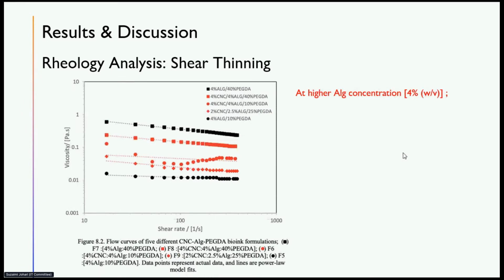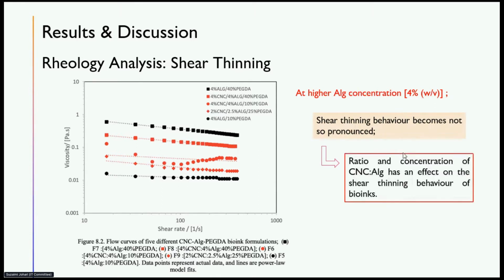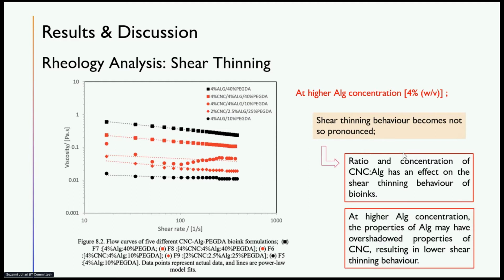Next slide. In figure 2, the flow curves show the other 5 formulations at higher alginate concentrations. At higher alginate concentrations, there is still shear thinning property, but it is not as pronounced as the shear thinning behavior at low alginate concentration. This may be because of the ratio and concentration of CNC and alginate. At higher alginate concentrations, the properties of alginate may have overshadowed or become dominant over the CNC. That is why the shear thinning behavior is also reduced at higher alginate concentrations.